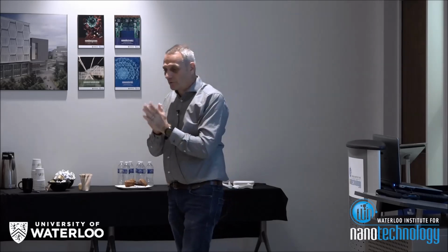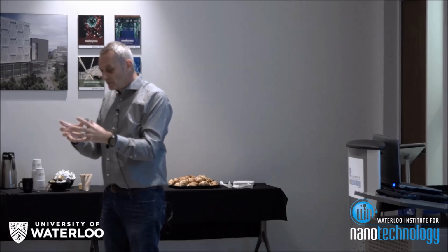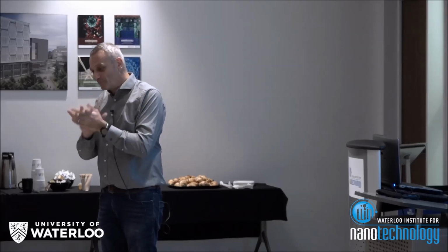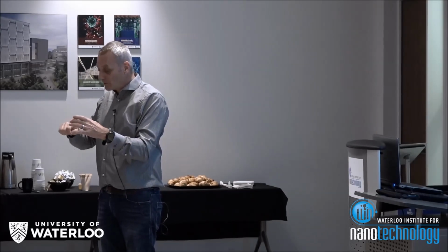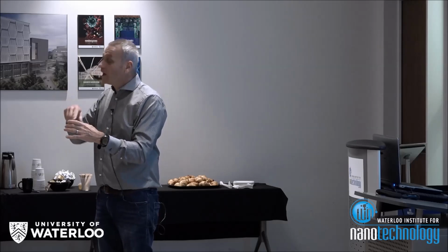One of the first experiments we wanted to do when we started to work in this field: we have an environmental scanning electron microscope, and because I'm in love with Plateau-Rayleigh stability, we said, okay, we are going to use a thermal stage under the SEM. We are going to increase temperature and see how the silver nanowires undergo the morphological instability. But we went up to 300, 400, 500, 600 degrees Celsius, and they were still intact.